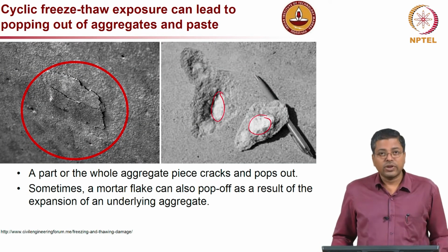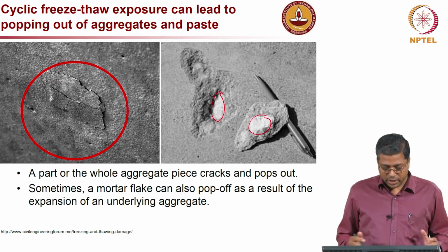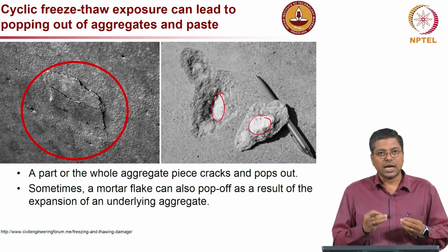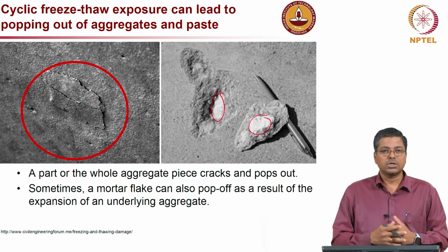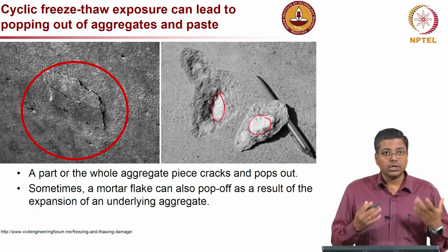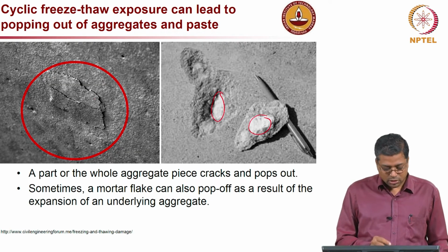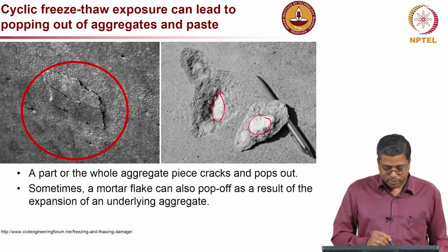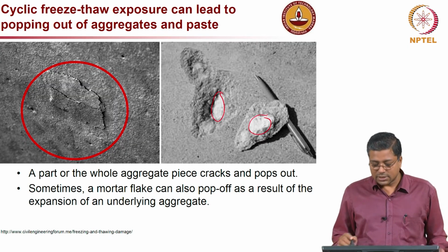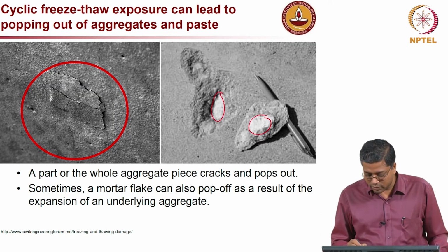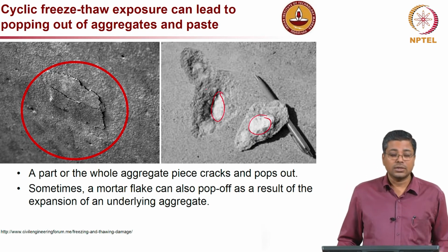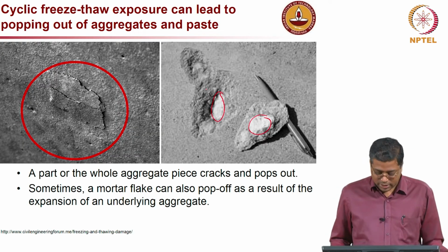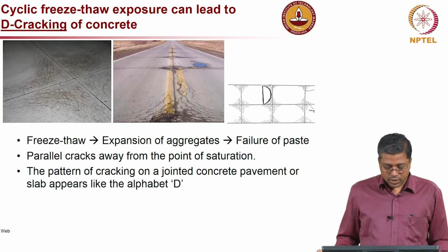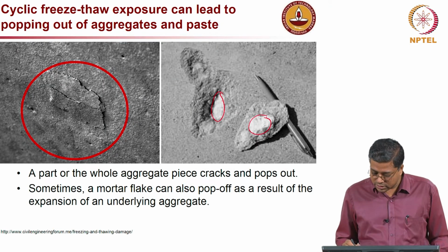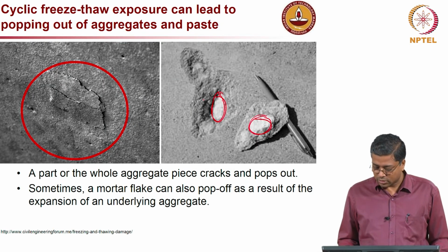Now, cyclic freeze-thaw exposure can also lead to popping out. You can see here. As we discussed, this ice will form inside the concrete, it will push the cementitious system and it will lead to cracking and popping out. As you can see on the picture on the left, it is a slight popping, it is about to pop, and then on the right side you can see that it is completely popped, and then you can very clearly see the aggregate is also cracked. The pressure is so much that it can also crack the aggregate. So, as you see here, this is the aggregate which cracked.